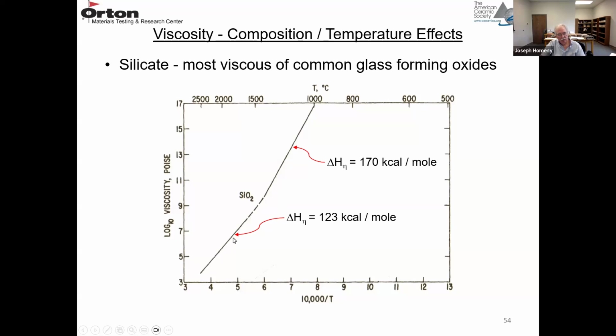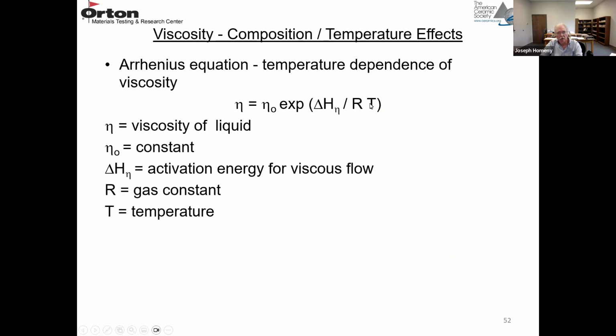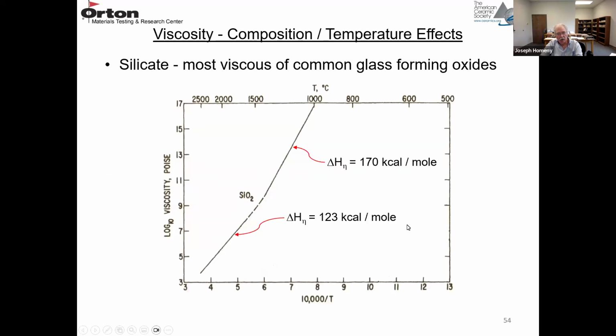The slope of these curves is given by this Arrhenius equation. If you do a log viscosity versus inverse temperature plot, ΔH_eta is the slope, the activation energy. In this case, it's 170 kilocalories per mole. And then it's common that as you increase the temperature, the activation energy changes because the slope changes. So it's a little bit lower here at the higher temperature, 123 kilocalories per mole. So you do a log viscosity plot, and you can calculate the activation energies.